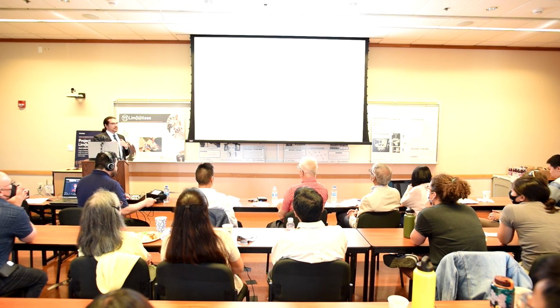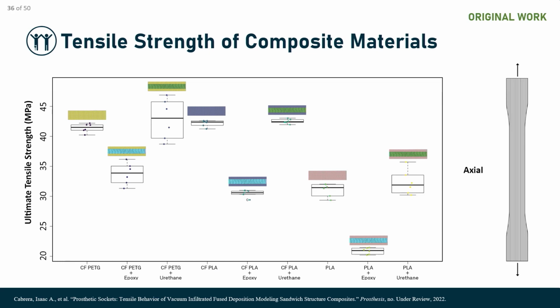Tensile strength is a little bit more complicated. In the axial direction, the strong direction, infiltrating with the epoxy basically decreased the strength in every case. However, infiltrating with urethane kept it about the same, and actually increased it in every case. So from this point of view, the urethanes are really looking quite promising.